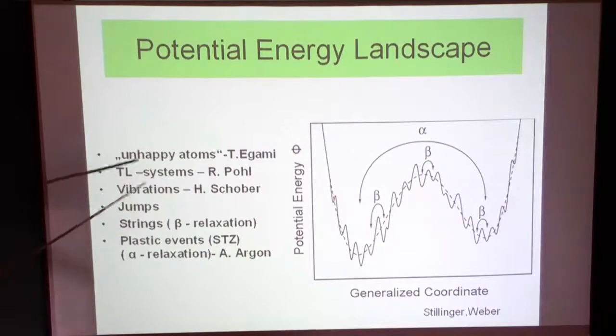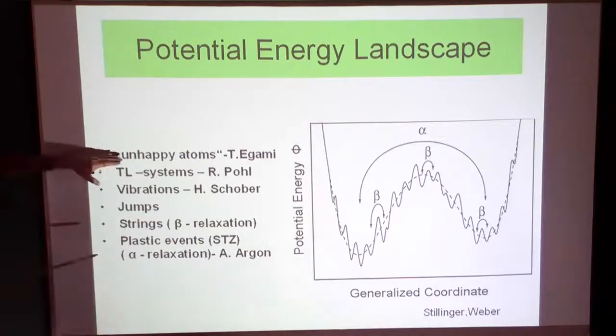So unhappy atoms means you're not sitting in the right potential minimum next to your neighbors, so they're under stress. And the reason why all these properties of the glasses and the supercooled liquids happen is due to these unhappy atoms, which produce huge atomic-level stresses. So the disorder and also the rearrangement, that's the cause of all that, in this lowest positioning at T equals 0, where the positions of the atoms are located due to this quench.